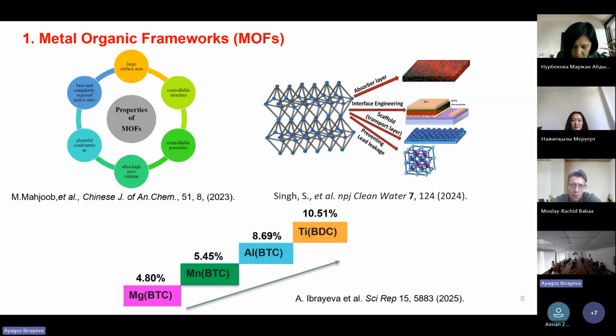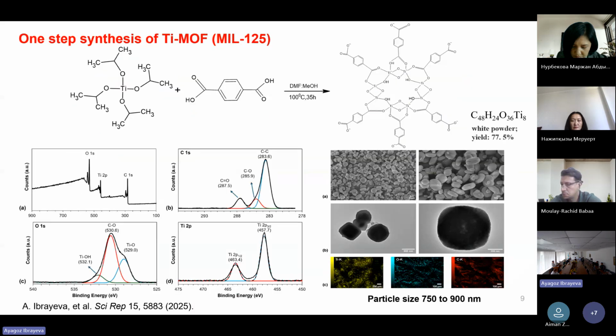Further, I will go deeper into this MOF, and by the one-step solvothermal method, we synthesized the titanium MOF. It gives us a white powder with a yield of 77.5%. Terephthalic acid was dissolved in DMF and methanol. Then we added titanium isopropoxide, and at 100 degrees for 35 hours, we obtained this product. The local activation states of this framework were obtained by XPS survey analysis.